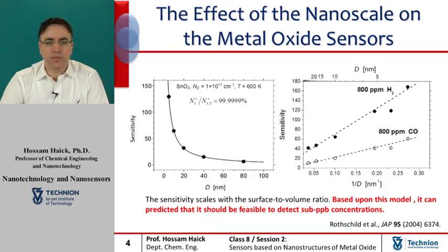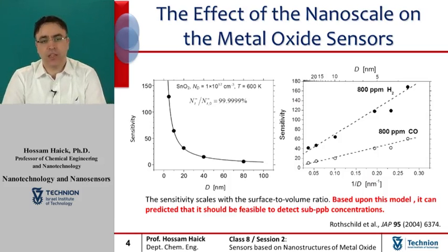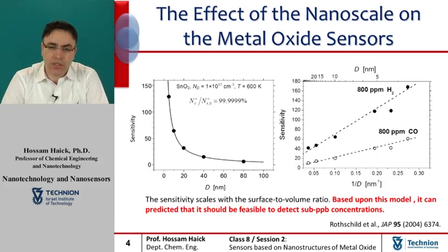In this case, the conductive core regime vanishes and the entire crystallite becomes depleted of mobile electrons. In other words, all electrons are trapped at the surface states. This situation gives rise to markedly enhanced sensitivity to variations in the density of these states due to the interaction with the gas phase.